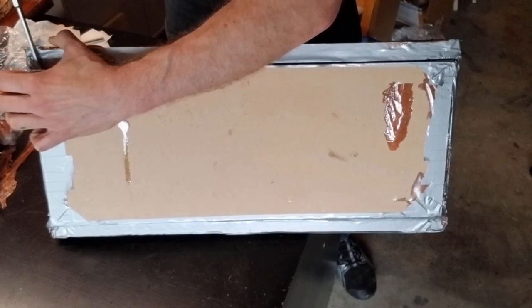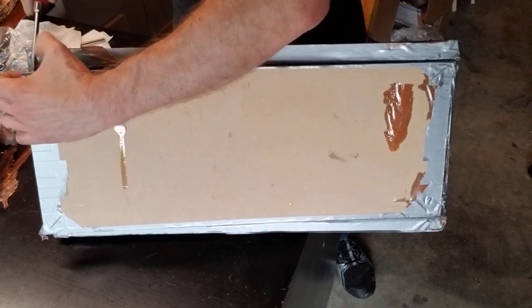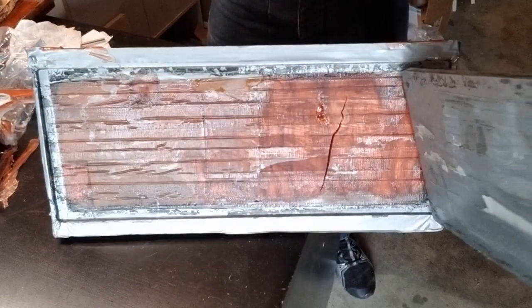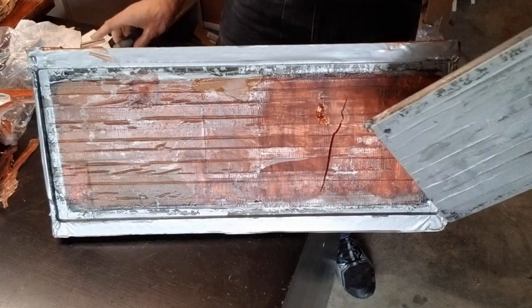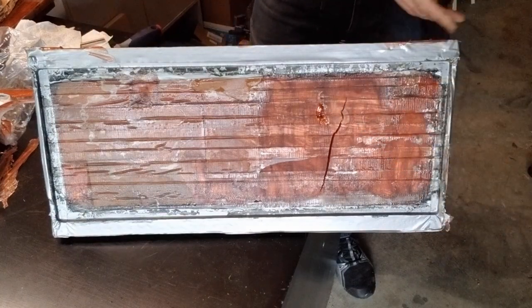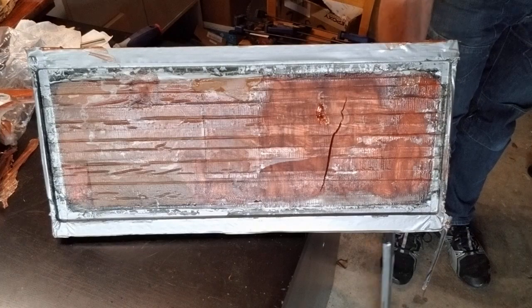The grease made it very easy to remove the panels. I noticed a crack in the epoxy, which probably happened because the epoxy got too hot, expanded and then shrunk too fast. It didn't run very deep, so I didn't worry about it, as the carve would go deeper than that anyway.